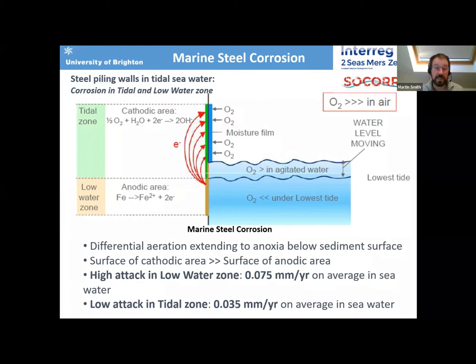Now, the reason for this is basically it starts out electrochemical. So if we take out the microbial factors, in the intertidal zone, we have steelwork that's exposed to air and forms a cathodic area where we're reducing oxygen from the atmosphere, and an anodic area where we've got submerged steelwork where we're oxidizing iron. And the interface between those two zones is well known for very high corrosion rates.